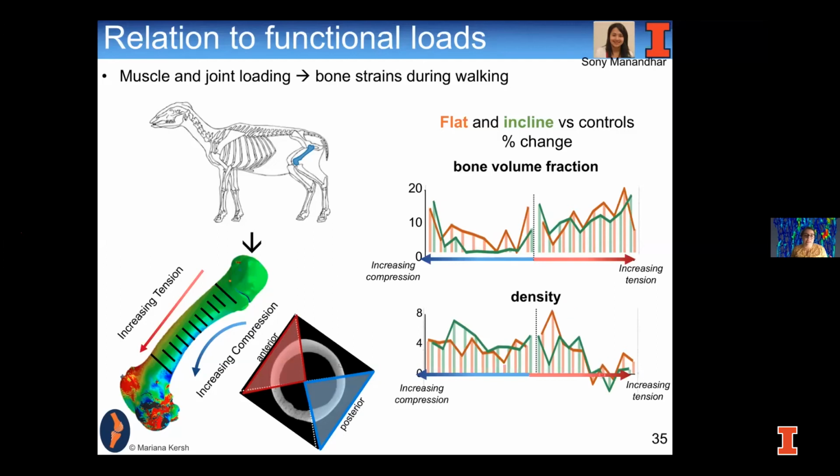And that is that in the same areas of increasing tension that induced a significant increase in bone volume fraction actually induced, again, no change or even a decrease in density. Whereas increasing compression and low levels of tension all seem to induce a density response that was fairly uniform. Again, we still need to investigate whether or not the fluorochrome labels that were induced would actually explain whether or not we are in the middle of a remodeling cycle, or whether this is really, in fact, a true response in terms of decreased density.